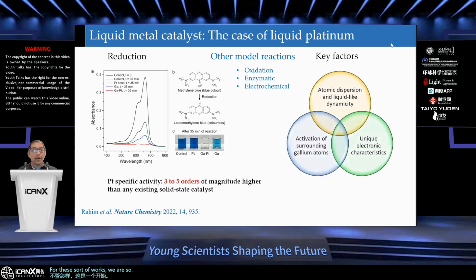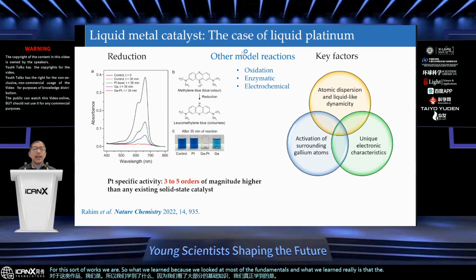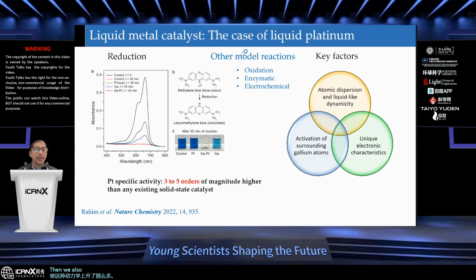What we learned, because we looked at most of the fundamentals, is that the atomic dispersion and liquid-like dynamicity play a huge role in getting these kinetics going up that much. Then we also noted that the surrounding gallium atoms get activated along with the active metal that you are using, and they show some unique electronic characteristics that I'm not going to go into in detail. You can get a pretty good picture if you go through the paper.